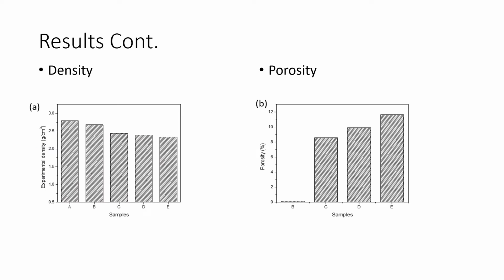Density decreased with increasing weight fraction of the reinforcement, while the porosity increased with increasing weight fraction of the reinforcement. The increase in the porosity was due to the formation of entrapped air bubbles, which were present in the microstructure as microvoids.